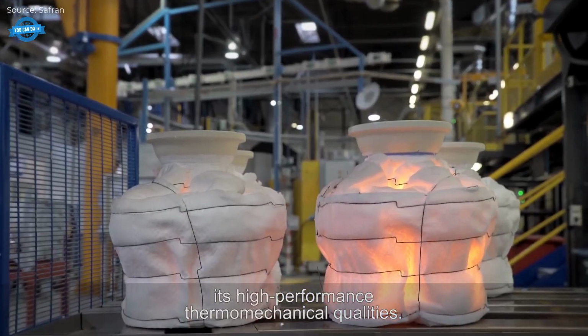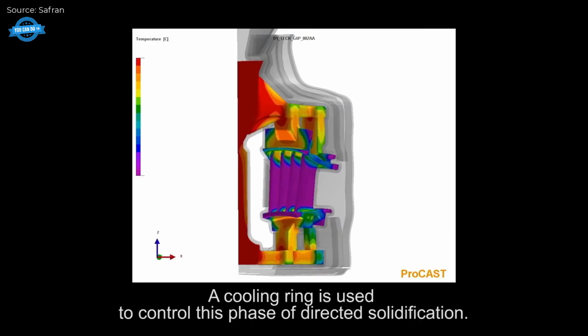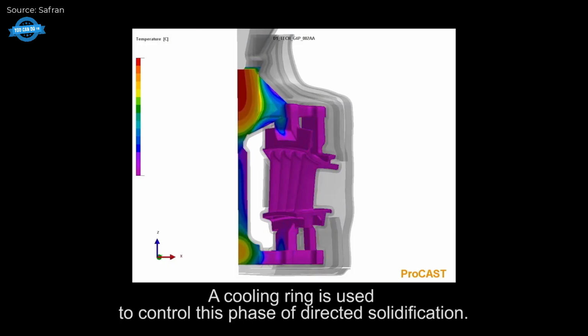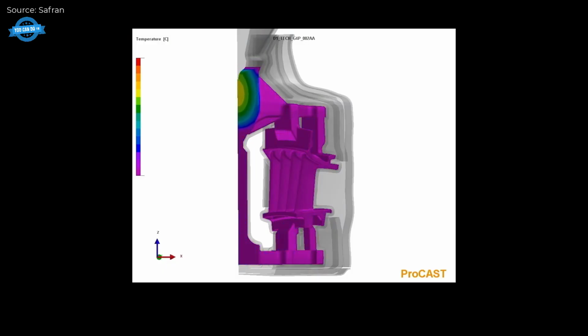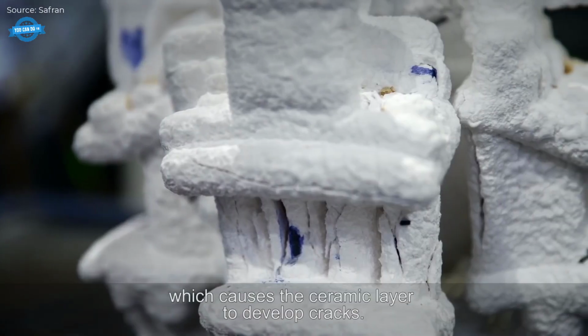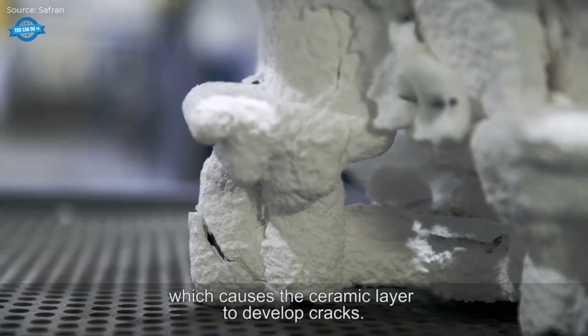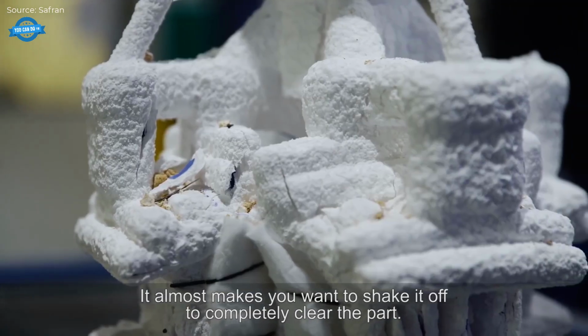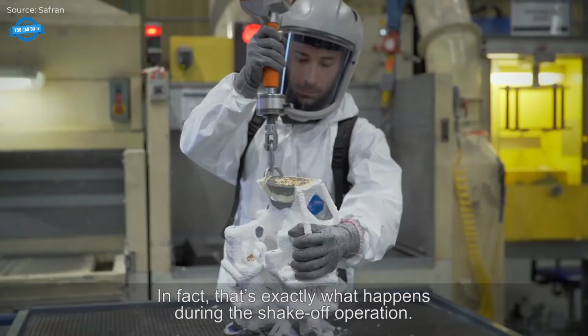During cooling, the ceramic shell typically cracks due to metal contraction. This allows for easier removal in the shake-off stage, where mechanical vibrations help clear away the remaining ceramic. Finally, the turbine blades emerge as rough parts, grouped in clusters. These are then separated into individual blades for further processing.